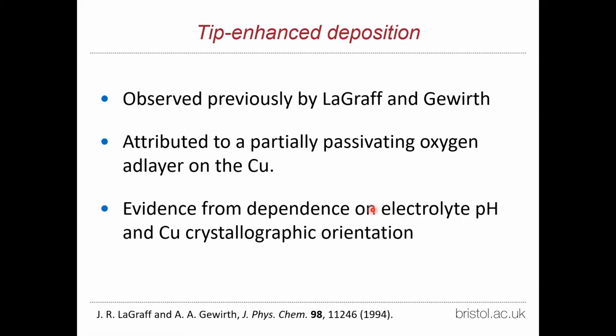Now, there could be many reasons for that. It could be an effect of stirring the electrolyte with the atomic force microscope, but it is, I think, more likely that the atomic force microscope tip is actually affecting the chemistry at the surface by removing a passivating, blocking layer of oxide. And previous workers, LaGraff and Gewirth, quoted here, did quite a careful study on this.